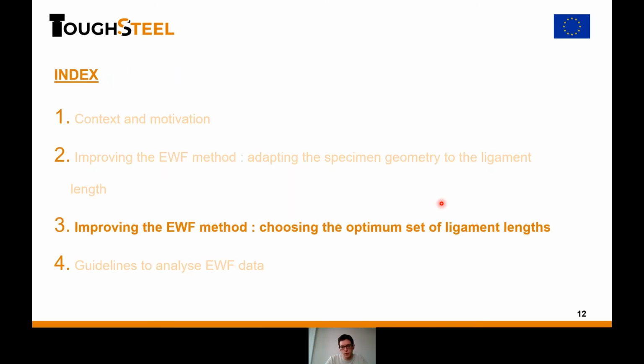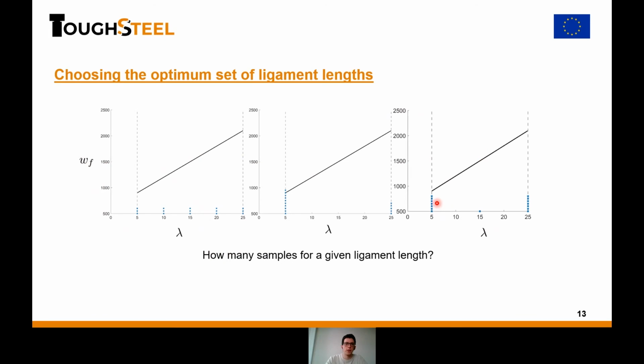So the second point is now, can we choose an optimum set of ligament lengths? Typically what you see, and what David showed, for instance, is that between the two bounds of the ligament length, we choose a number of samples to test, and then we space them in an equidistant manner between the two bounds. So for instance, if we have 15 tests, we would try 3 tests at 5 millimeters, then 3 at 10, 3 at 15, 3 at 20, and 3 at 25. And we are happy with this.